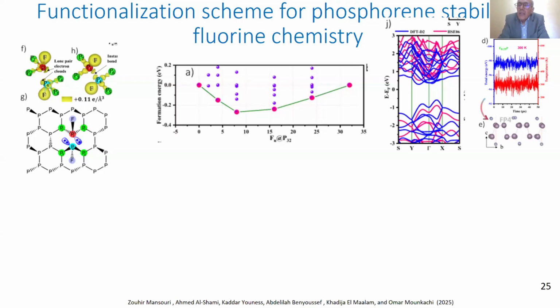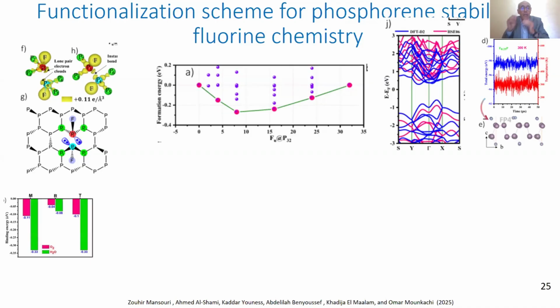We see that the band gap still shows semiconductor behavior with an opening gap, and molecular dynamics shows the stability of this phosphorene with 25% of fluorine on the surface. It is stable at room temperature. It is stable, but does it protect the phosphorene from oxygen and water?